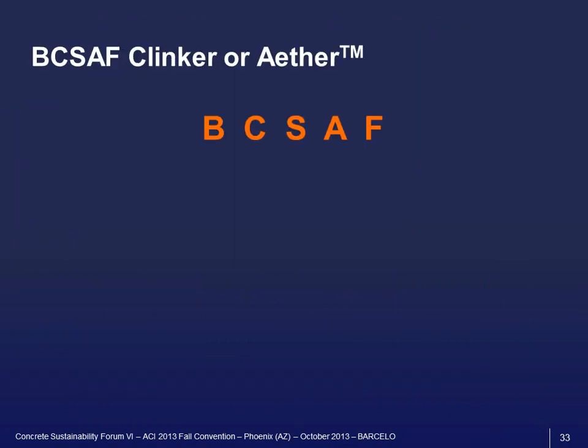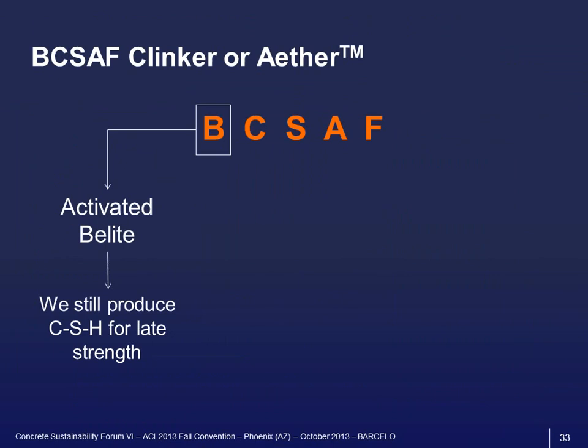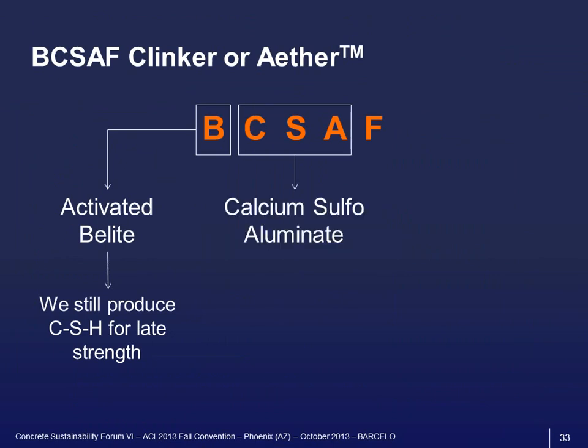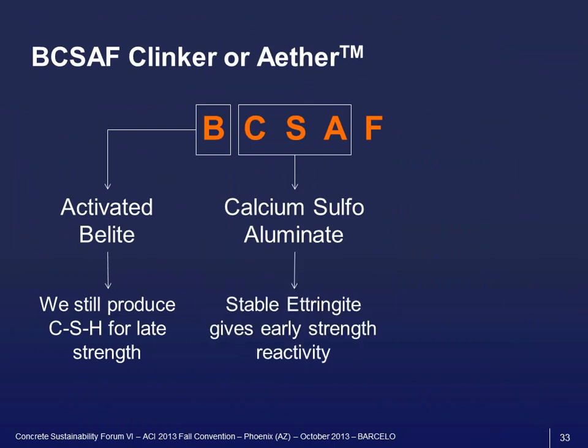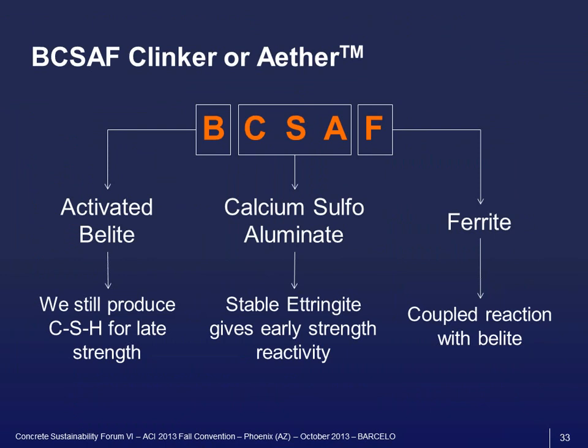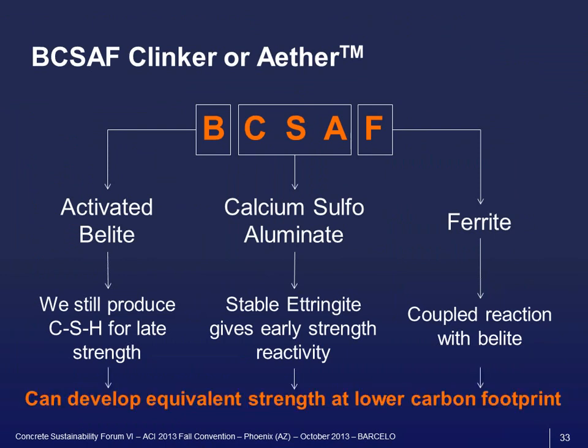So what we are proposing is BCSAF clinkers, and we have trade named them Aether. So B stands for belite, and here it's really activated belite that we are using. We are using boron to dope belite, and it's a different polymorph of belite that we are making, which is more reactive than the belite we find typically in OPC. So we still produce CSH for later age strengths. CSA is the calcium sulfoaluminate phase, and we produce stable ettringite that gives the early age reactivity. And F stands for ferrite, and ferrite is also quite important because it reacts, and there is a coupled reaction with belite to form strätlingite. And the result of all this is that we can develop equivalent strengths for a lower carbon footprint.